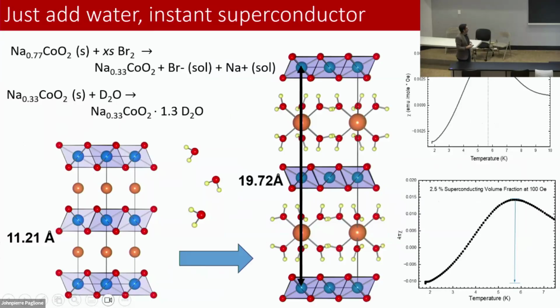She's made the compound. You start out, again, just a conventional solid state technique. Sodium, I think she used sodium carbonate or some kind of hydroxide, I don't remember which one, with cobalt oxide. And then you just fire it up, you make your compound. Then you add the bromine. I forgot to add here, you put it in acetonitrile solvent so that it's not too difficult of a reaction. And you remove sodium because the bromine is going to oxidize the cobalt. And the sodium just pops out when you do that, okay?